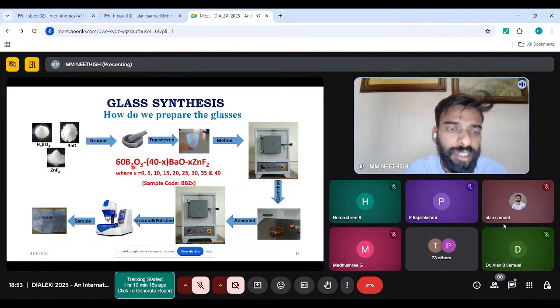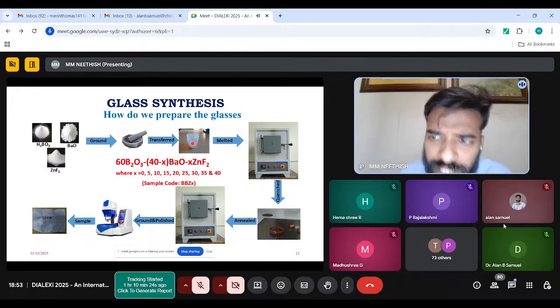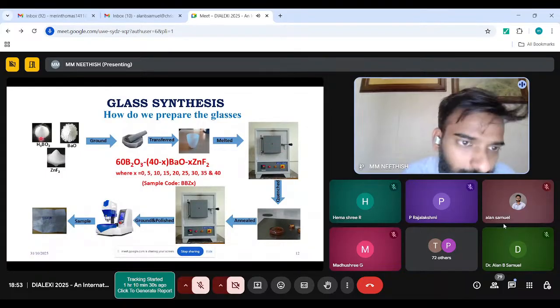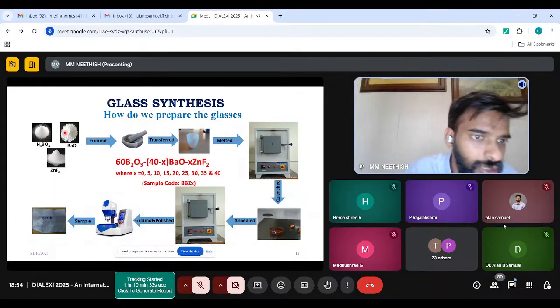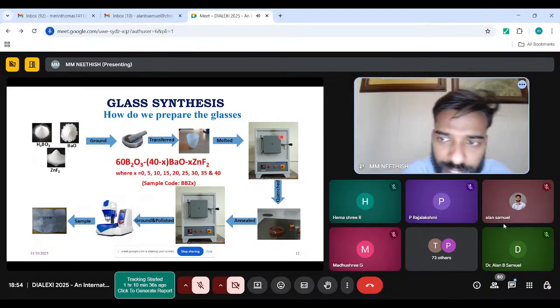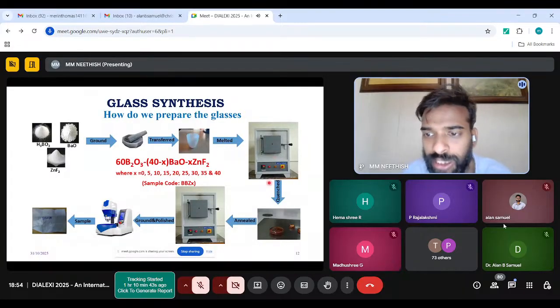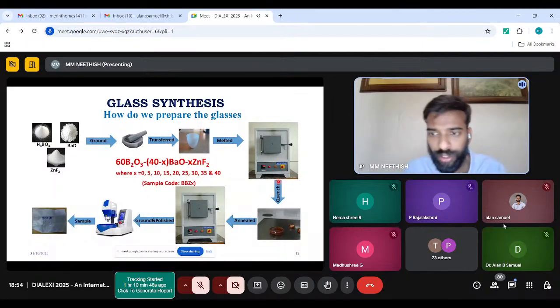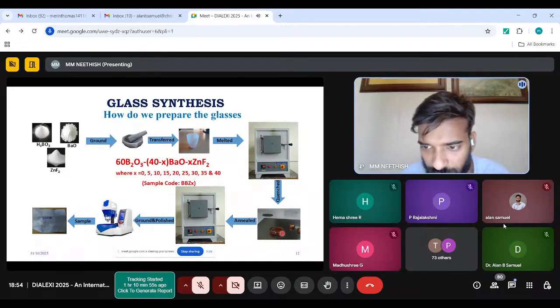You take the constituent chemicals which you want to make into glass. You take them and, using a mortar and pestle, you grind them and transfer them to a crucible. Then you melt it in a furnace. You have to know the temperature where it gets melted, because these mixtures behave differently than individual chemicals. So you have to find the temperature at which it melts. Then you go there and melt it and keep it for some time to have a uniform melt. Then you bring it down to room temperature or a low temperature. Then it forms the glass. So you can see it here. It's really beautiful, like beads of glass. You get exactly like this.